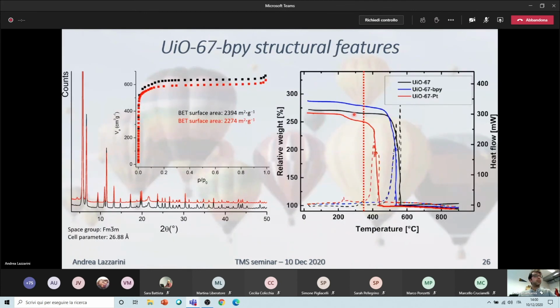As I told you, metal organic frameworks are crystalline. As you can see by diffraction, having several very sharp peaks, you have a very crystalline material. And by performing nitrogen adsorption, as I told you before, we reached a surface area that is close to 2,400 square meters per gram. So having 1 gram of this sample, you have several hundreds of square meters available to deposit your active phase. And even after the functionalization with the platinum chloride species on the bipyridine ring, we maintain a very crystalline system and very high surface area.